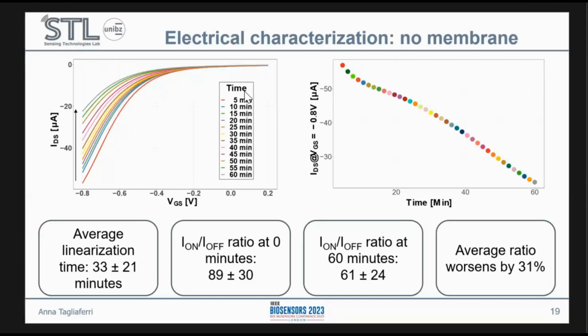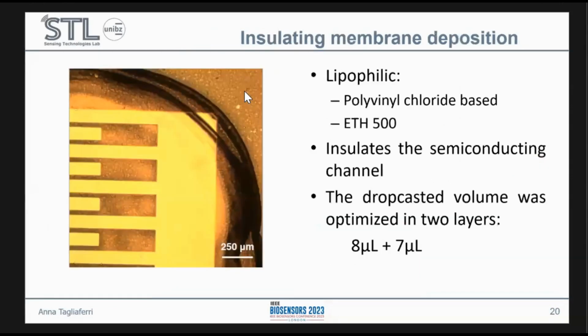After checking that the performance is worse, we then deposited our membrane, our insulating membrane, on the carbon nanotubes. The membrane is polyvinyl chloride based, and the lipophilicity is given by this ETH 500 compound. The membrane is there to insulate the semiconducting channel and to protect the carbon nanotubes from the environment, that is from the air and from the electrolyte.